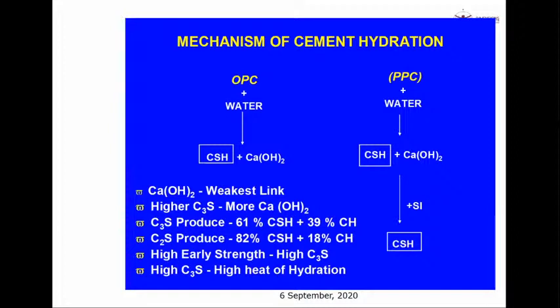So why is it important to understand this? Because the 28-day strength is a kind of misunderstood figure. In situations where you can afford to wait, where you are not in a hurry to get the 28-day strength, even if you can wait for 56 days, then there are enough possibilities where you can use lesser quantities of cement and get a cheaper concrete, but still ensure that the engineering parameters are met. Not at 28 days, but at 56 days.